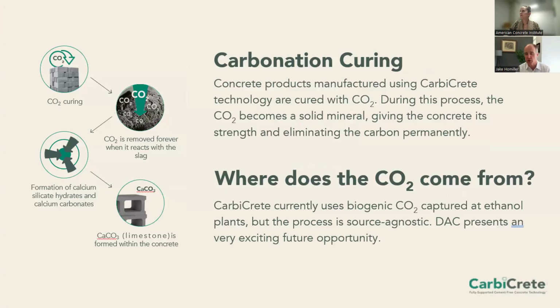So carbonation curing. This is what's happening when we introduce CO2 in the chamber with water and the steel slag that's part of the overall mix. During our process, the CO2 becomes a solid mineral, so it's reacting with the materials that are in the steel slag to create calcium carbonates or calcium silicate hydrates. And that's fundamentally what gives the strength to the CarbiCrete products.